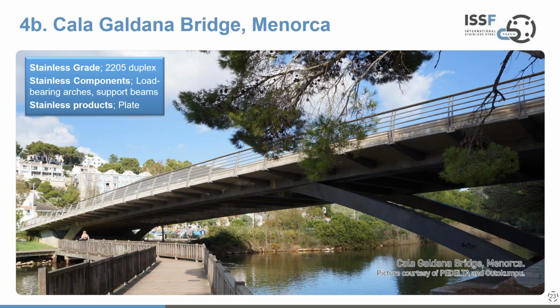So we'll start in the Spanish island of Menorca with the Cala Galdana bridge. And this bridge was built using 2205 duplex stainless steel, which is one of the standard duplex family of grades. The stainless components were the load-bearing arches and the support beams, and this was supplied as hot-rolled plate. And this is an example that demonstrates that when considering bridge building with stainless steels, we're not just looking at long products like reinforcing bar. Flat products have a big role to play as well.